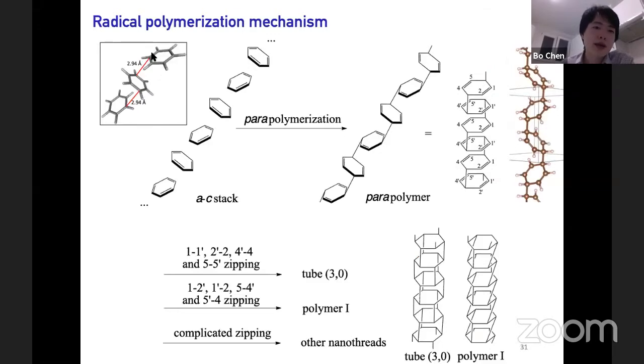The T stack, on the other hand, seems to be compatible with what we call a paracycloaddition polymerization, where each molecule forms one bond up, one bond down, giving us this degree-two polymer, which we call a para-polymer. And in this polymer, we have two double bonds remaining in each ring. And if you polymerize the remaining double bonds in different ways, we will end up with different types of threads. The tube and polymer I can come from this mechanism.